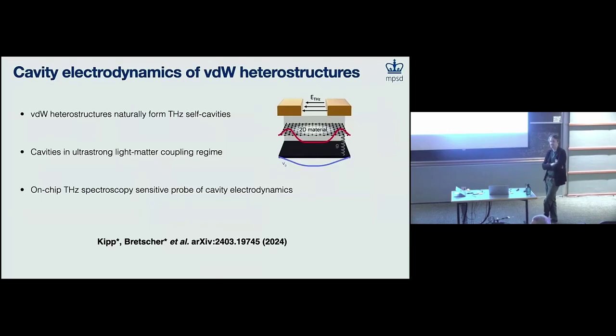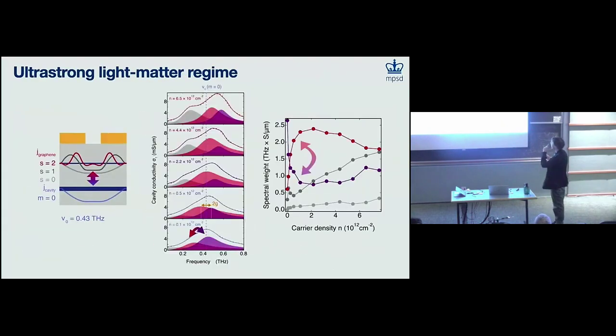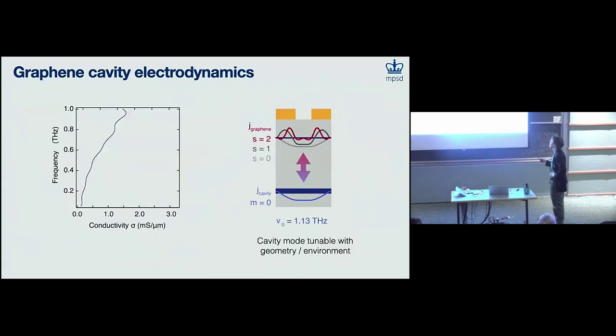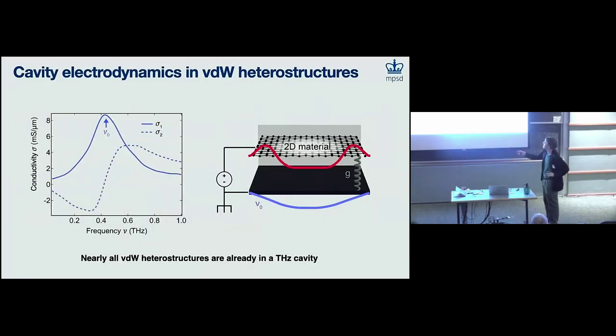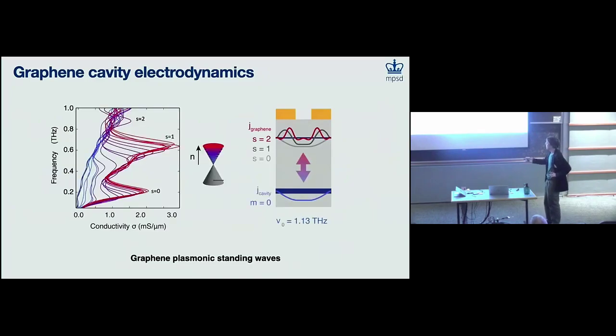Thanks for the very nice talk. How does the anti-crossing compare with the line width, and what's the line width of the mode? Okay, good question. The line width is not great in these measurements. Fortunately, thanks to how the pioneers of this field have chosen to define strong coupling versus ultra-strong coupling versus mega-strong coupling, for ultra-strong coupling the line width doesn't matter, at least according to how it's defined, because as you can see, this is fairly broad. This is not going to zero, zero's over here somewhere, but the Q factor of a cavity mode is 3 or 4. Now in the graphene, for example, this mode here, it's something more like 7.